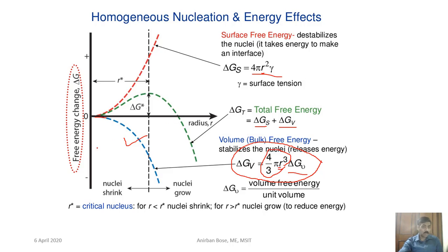Now you observe about the total free energy change. Observe what is happening about the total free energy change. What we know, that actual transformation will always take place if the free energy change decreases. Okay, so here you can see up to a particular radius, this x-axis corresponds to the radius of the second phase. So up to a particular radius, you see with the increase of r, the net change of free energy is increasing. That means within this region it is in the embryo state.